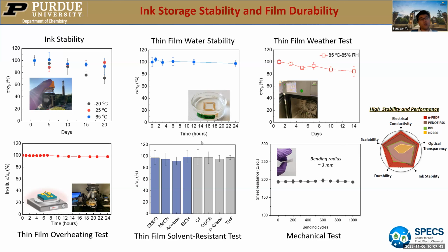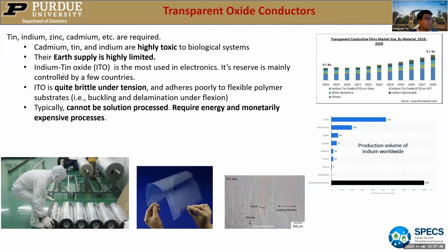As I said, n-PBDF is transparent as a conductor, so it has the possibility to replace ITO as a conductor. So what's the problem with ITO, the transparent oxide conductor? The mineral supply is limited. It's also somewhat toxic in bioelectronics. For example, indium is the most used one, but its reserves are mainly controlled by a few countries like China. Also ITO is quite brittle, so it cannot bend or be made on a flexible polymer substrate. And it cannot be solution processed, which may cause problems in manufacturing.